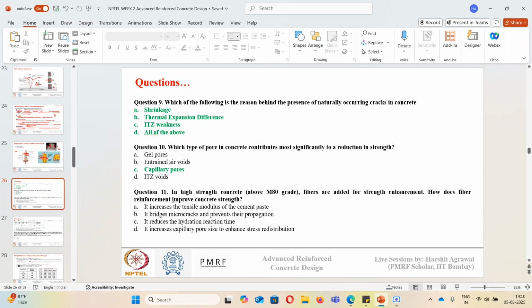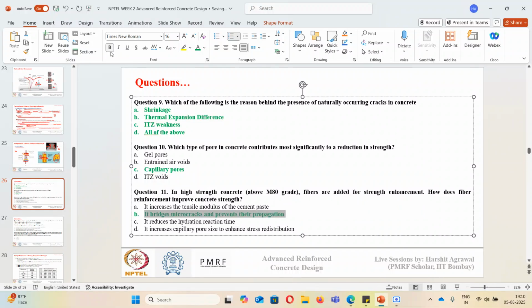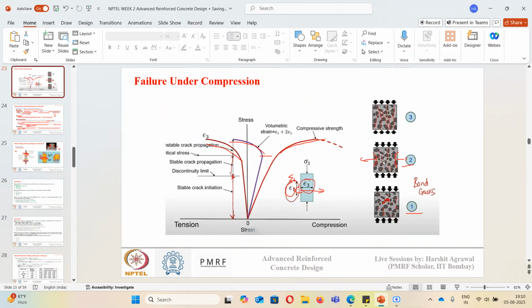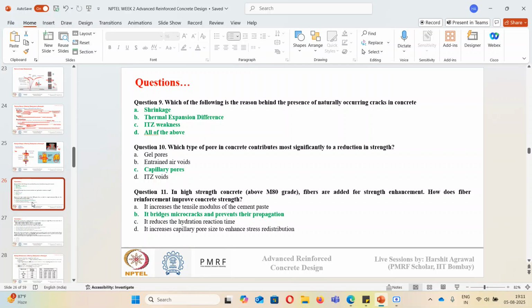How does fiber reinforcement work? They bridge the micro cracks and prevent their propagation. We saw when we talked about how the failure happens that initially cracking starts at ITZ, and then these micro cracks connect with each other. So what happens if fibers are present in my concrete matrix? Fibers will bridge these micro cracks from growing, and delay their propagation. If their propagation is delayed, the failure planes won't form easily, and thus it will improve the strength of concrete. That's why in high strength concrete, generally above M80 or M100, fibers are commonly used in mixture proportioning.